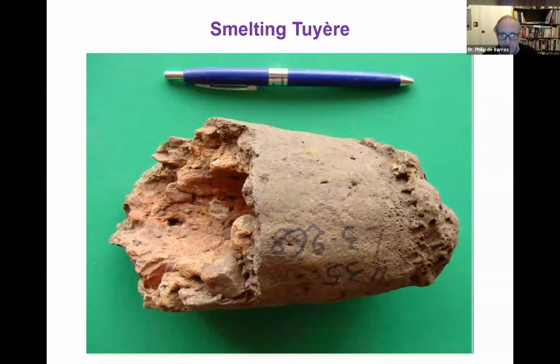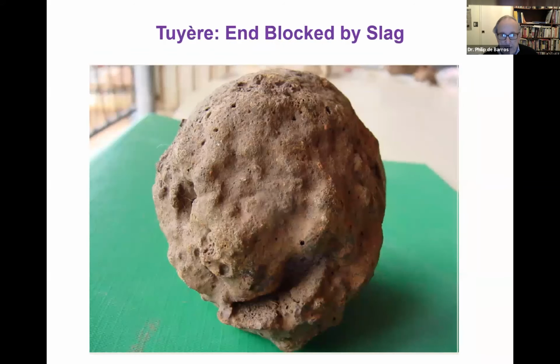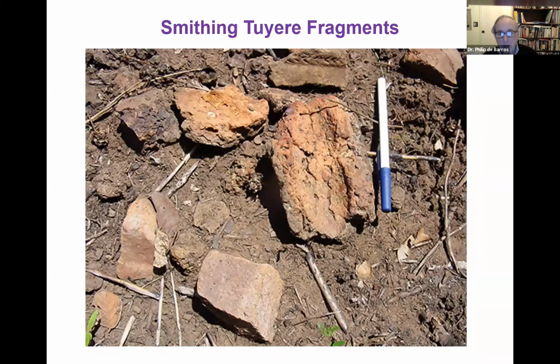This is an example of a smelting tuyere fragment, and it's been completely clogged with slag, which happens sometimes in the furnace during smelting. This does not occur with smithing tuyere fragments. Sometimes the end melts and you get a little slag around it, but it's rarely plugged with slag because the temperatures aren't as high in the forge as they are in the furnace.